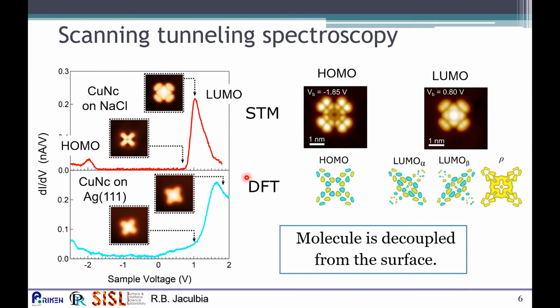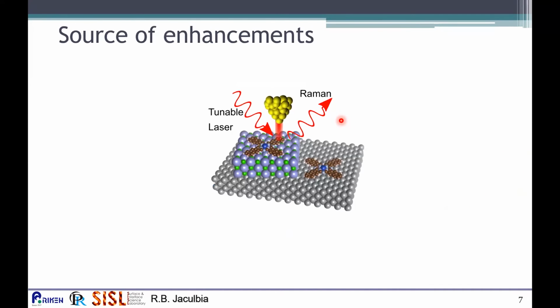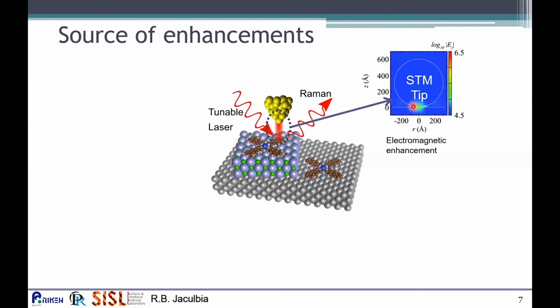Then the implication of this for Raman spectroscopy, and specifically for tip-enhanced Raman spectroscopy, can be understood when we look at the enhancement mechanisms in both SERS and TERS in our case. For tip-enhanced Raman spectroscopy, the Raman signal is enhanced by two or three kinds of enhancement. First is the electromagnetic enhancement, wherein both the incident light and the outgoing Raman light are enhanced by the presence of the metal tip.